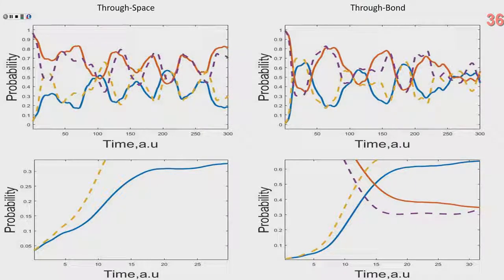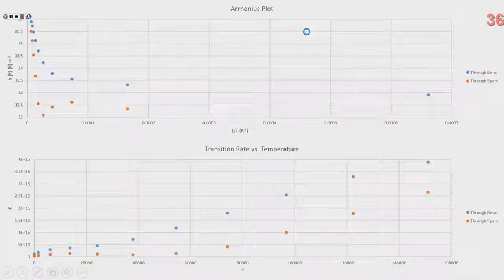So you zoom into these graphs, you just look at this section here and this section here, and you figure out the slope of this linear region to figure out the rate at which the electron is transferring into the perovskite. And you end up getting these transfer rates, which have unphysical temperatures, but you end up getting a very interesting phenomenon where the Arrhenius plot certainly doesn't obey the Arrhenius equation, because if it did, the Arrhenius plot would appear to be linear. Instead, it appears that the transfer rate is directly proportional to the temperature of the system.